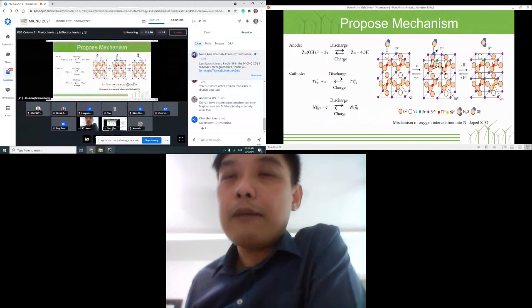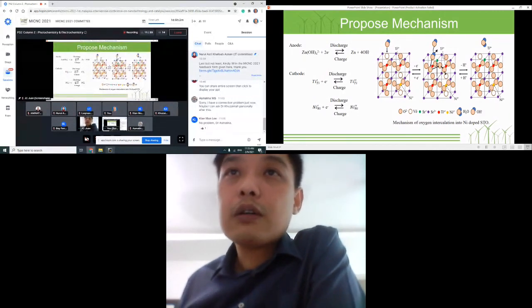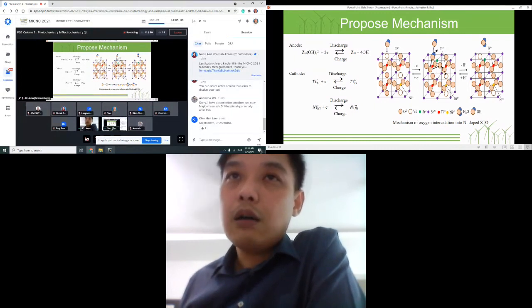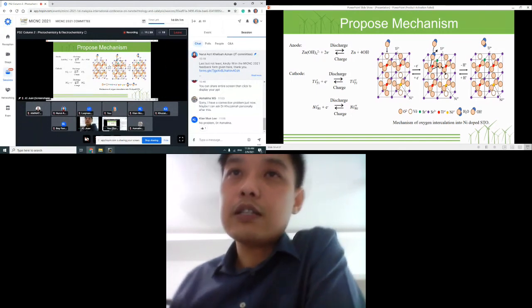This is what I'm saying about the mechanism here. What we've found is that, in the first report using this perovskite material, it can be used as a cathode material for this rechargeable zinc battery. On top of that, we also first report the importance of oxygen vacancy in battery research, which was poorly understood previously. By introducing what we call oxygen vacancy, this means a lack of oxygens in these lattice structures.